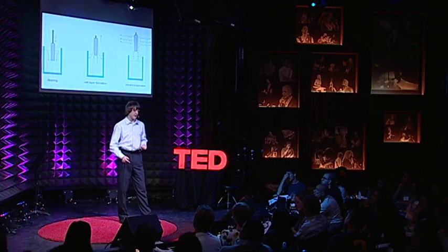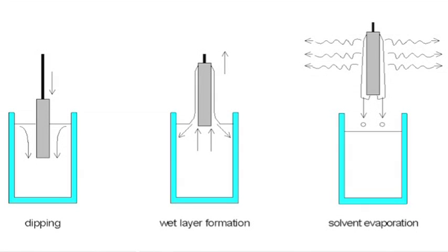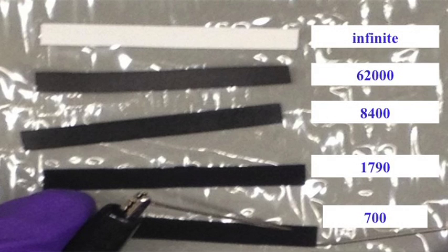So then, what I had to have is a substrate that can support this network of antibodies and carbon nanotubes. And I thought it had to be porous to take up this aqueous solution, but also it had to be inexpensive and readily available. Filter paper fulfills all of these. And basically all you have to do is create a uniform dispersion of these antibodies and carbon nanotubes that are just floating around, chilling out. And then you just dip coat your sensor, making it really easy to produce. And so here's a visual depiction of the sensor being created. And how you test it, it only requires a sixth of a drop. And you just put it on, and then you just measure the change in electrical potential, just an electric parameter.